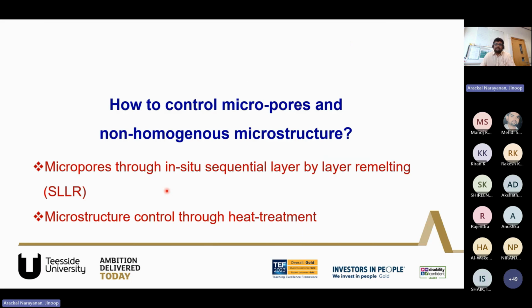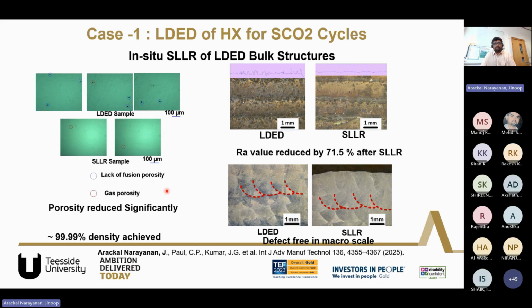So we had certain issues. One is the non-homogeneous microstructure. We had microporosities during the manufacturing. So these need to be taken care of. So we used a method called in situ sequential layer-by-layer remelting, where we did remelting during the manufacturing itself, which was recently published in the International Journal of Advanced Manufacturing, where we use laser scanning to control the porosity, surface roughness and the microstructure. So we could get close to 100% density, and the Ra value reduced significantly.